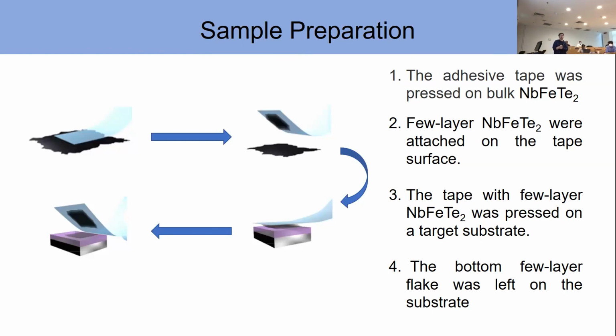To study the 2D magnetic properties of NFT, we prepare NFT flakes down to only a few layers. The procedure is shown in this slide, and it has four steps. The first step is to use blue tape to press on the bulk crystal of NFT. Then we detach the tape, and now few-layer NFT is attached on the tape surface. Next, we attach the tape to our target substrate, where we will make our device. When we detach the tape again, the bottom few-layer flake is left on the substrate.